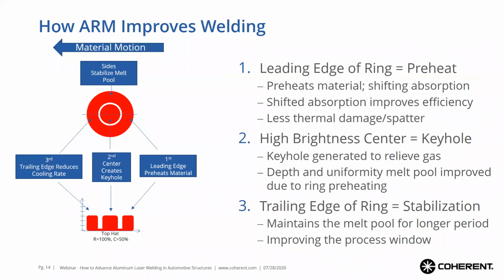What makes the ARM laser unique, and how will it improve your welding? There are basically 3 steps. You have the large outer ring, which preheats your material. That helps shift the absorption and improves the efficiency of the coupling, which gives you less thermal gradient, so less thermal damage, as well as reducing your spatter. The high brightness, smaller center or core generates a very stable keyhole, providing uniformity in the depth and overall process improvements. And then finally, that ring also helps stabilize by maintaining the weld pool longer. It gives you additional heat to reduce the cooling rate, which helps improve your process window.